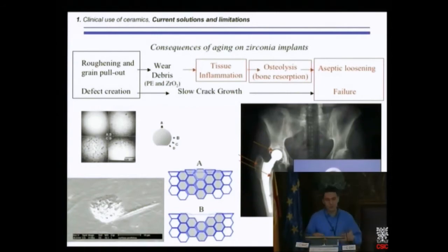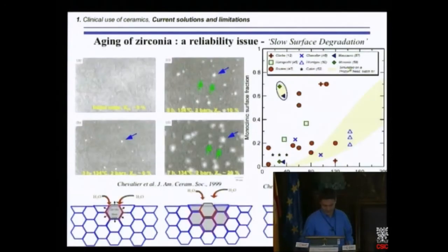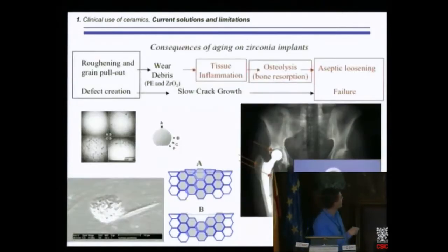Also, this is a micro-cracked zone because, as we said, the grain, while transforming, leads to microcracks all around the area. So grain pull-out is quite easy. So roughening and grain pull-out. Here is the surface of zirconia femoral heads after some years in vivo. Not many years. I don't remember exactly, but 3 to 4 years.